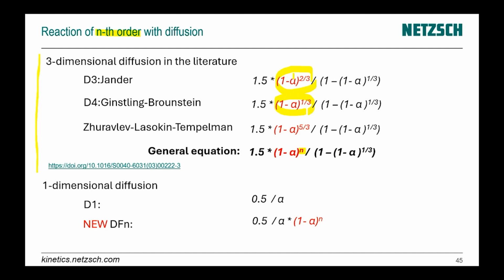So this is very nice. For different models, n is different. We can just select one of them and make a fit very well. But for 1-dimensional diffusion, it is not the case. We have only reaction D1, where we have 0.5 divided by alpha, where alpha is conversion, and it is independent of n. It is independent of the part 1 minus alpha to the power n.